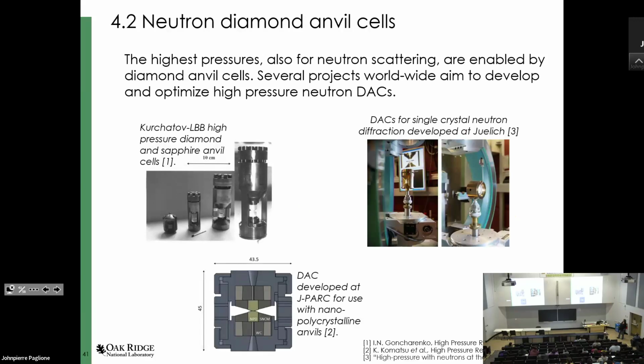So neutron diamond anvil cells have been developed all over the world for quite some time. The initial work by Igor Goncharenko did a lot of really nice work on hydrogen, various quantum materials in France. So if you're interested in that, there's quite a large body of work. These cells were limited to 40 GPa or thereabouts. There's also been recently quite a push in Germany where they are developing diamond anvil cells that they can couple with low temperature, so they are all made from copper beryllium. But currently their source is down, so they are not pushing that further.